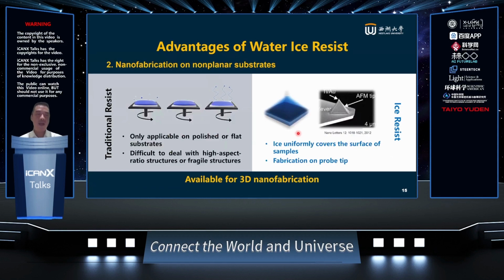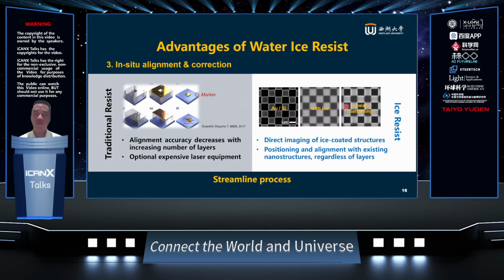And the second advantage is that because we evaporate ice on the substrate, the ice uniformly covers the surface of samples, whatever the shape is. So it's a conformal coating of the films. This is different from the traditional resist, where you need to do spinning, and that can only, or at least not so easily, be done on curved surfaces, but only on planar surfaces. But actually, for example, we can do lots of things, including making a tiny titanium and gold tip on an AFM, and that can actually be done. I will give an example later on ice lithography on fibers.